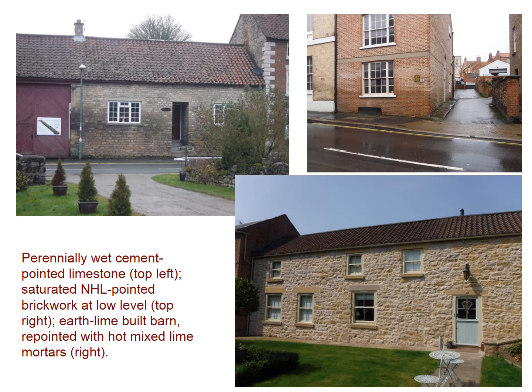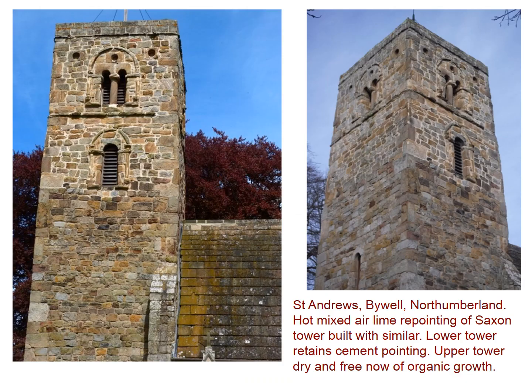Perennially wet cement pointed limestone at top left. I look at this every day out of my window. Saturated NHL pointed brickwork at low level, top right. Earth lime built barn repointed with hot mix lime mortars on the right. I don't need to say much more. Similarly dry fabric at the top of this tower in Bywell, Northumberland. Hot mixed air lime repointing of a Saxon tower built with very similar proportioned mortars. Lower tower retains cement pointing. The upper tower is dry and free now of organic growth.